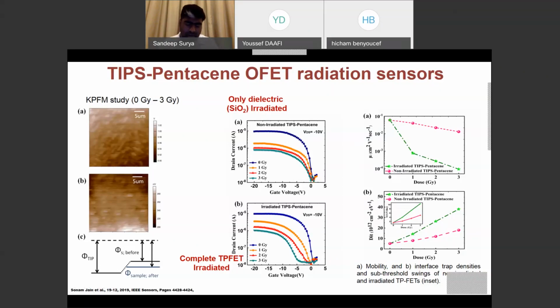So the change in threshold voltage is mostly attributed to the generation of interface traps and bulk traps, especially from TIPS-Pentacene, and not just due to the generation of traps within the silicon dioxide. One can see on the right side the comparison of the mobility of the TIPS-Pentacene irradiated device and the dielectric irradiated device. In the case of TIPS-Pentacene, the initial first 1 Gray has caused about 2 orders of change in the mobility, and then 1 more order till you reach 3 Gray dose. But in the silicon dioxide irradiated device, you hardly see one order of change from 0 to 3 Gray.